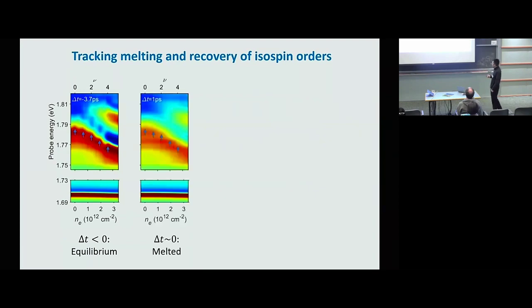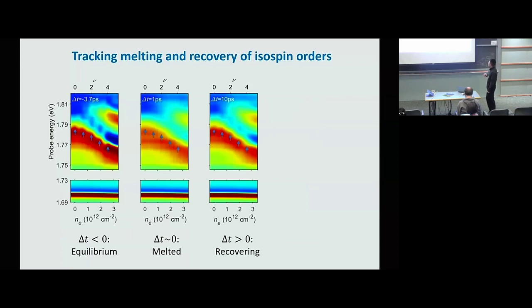And then, let's look at a different delay. This is 1 picosecond after the pump light arrives. And we know the pump will excite graphene, and these excitations can be monitored from the absorption in the nearby WSe2 layer. What we found is that these cascade features are melted. That's not too surprising because we dump a lot of energy into graphene, which will make the electron temperature very high, which will melt all the orders. And then if we look at 10 picoseconds after time 0, we can see that these cascade features